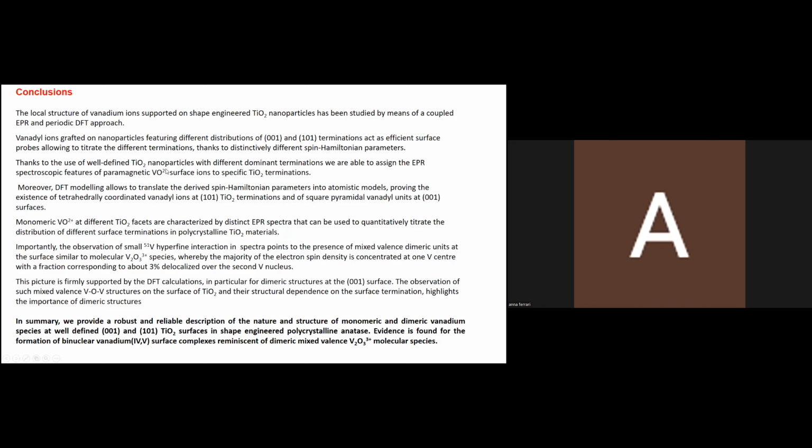Thanks to well-defined nanoparticles with different dominant termination, we were able to assign the spectroscopic features to paramagnetic vanadium at the surface and correlate the signal to a specific termination. The DFT modeling allows us to characterize these different structures derived from the experimental indication.